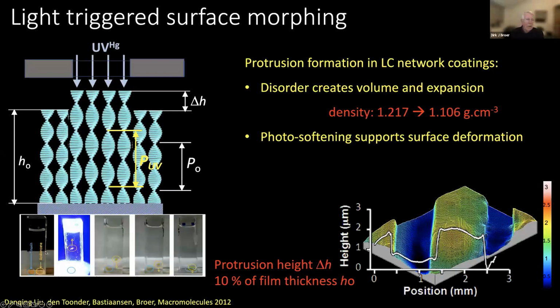And that we could easily demonstrate by immersing the films into a salt water solution. The salt water has a density just a little bit lower than the density of the polymer, and then as soon as you expose it with light, the film starts to float. And then if you switch off the light, it starts sinking to the bottom again. We also have a reference here. In this case, we exchanged the azobenzene compound by another compound which has the same absorbance as the azobenzene. And what you see is basically that the sample remains on the bottom. So simple warming up of the sample because of light is not the mechanism here that's responsible for the density decrease.